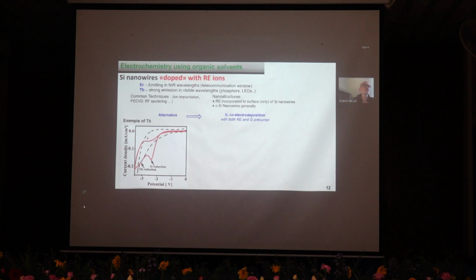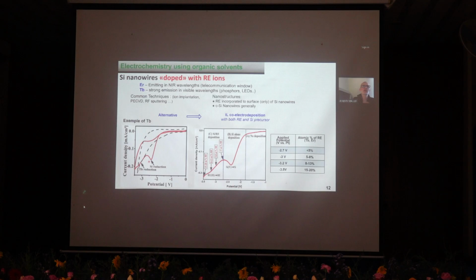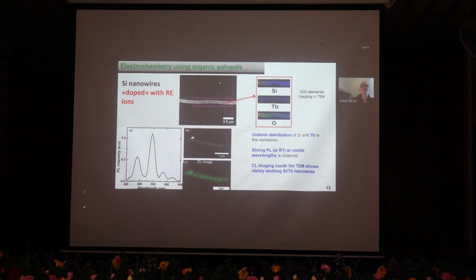Here we also try to do some doping on the silicon. We use erbium and terbium precursors. It gives us the possibility, which is normally obtained by ion implantation. Here we can grow a co-deposition of silicon and those rare earths, giving us different possibilities of having different content of those rare earths like terbium or erbium. Here, for instance, is some optical characterization, photoluminescence and cathodoluminescence measurements confirming the presence of terbium on silicon. This is EDX showing how homogeneous it can be.